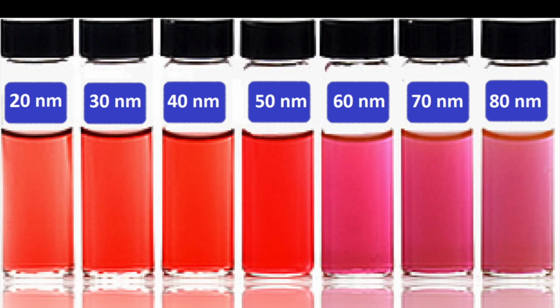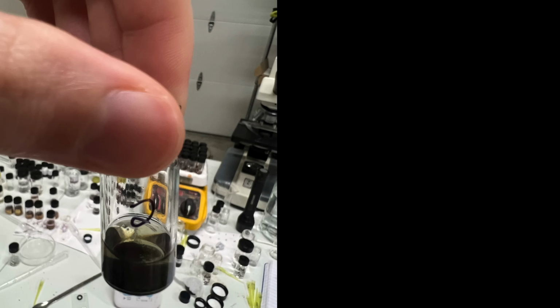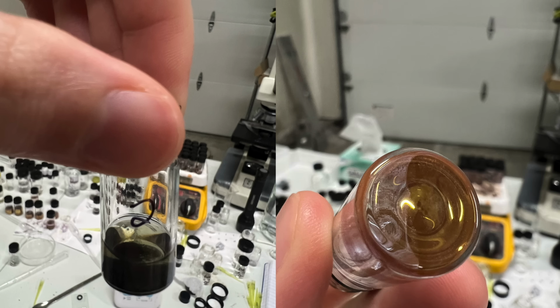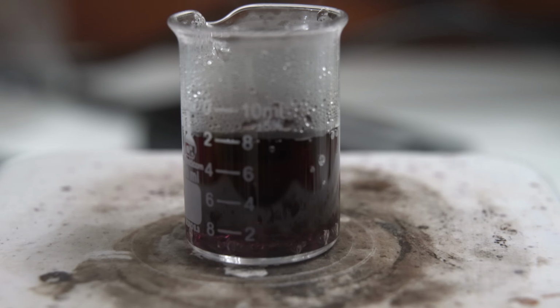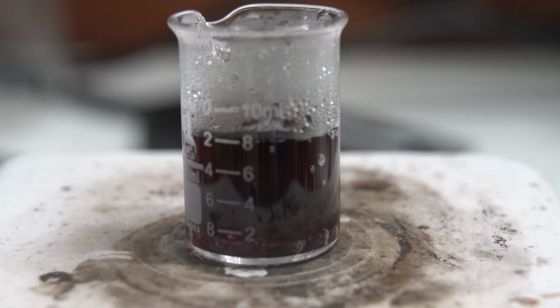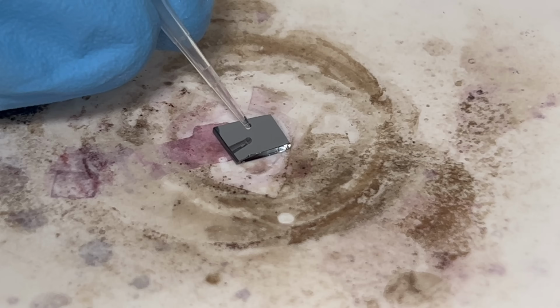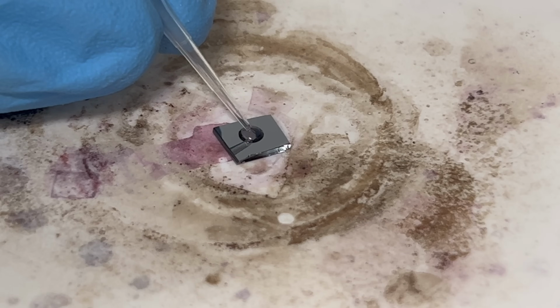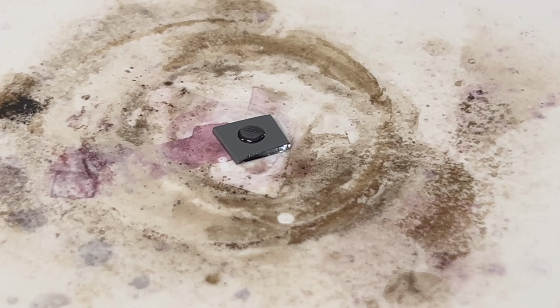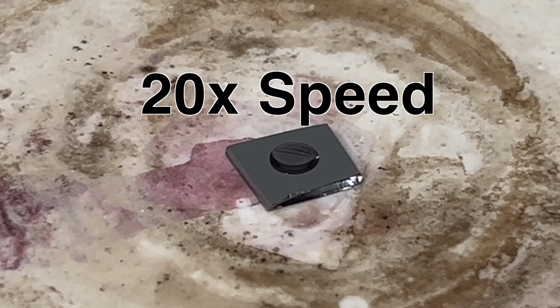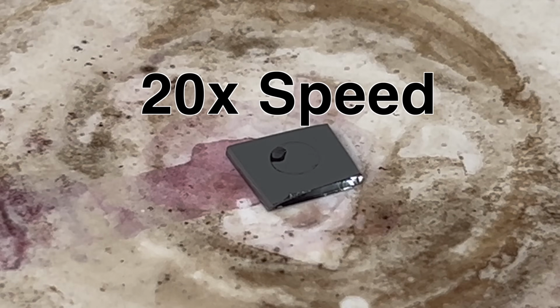This property is only really noticeable when the gold particles are smaller than a couple hundred nanometers. If the particles are larger, then they'll start to appear as black and then shiny gold. Based on the color, it looks like our nanoparticles are probably somewhere between 50 and 100 nanometers in size. I used a micropipette to place a drop of the nanoparticle solution onto a silicon wafer, and then placed it on a hot plate to gently evaporate the liquid, hopefully leaving behind our nanoparticles on the silicon surface.